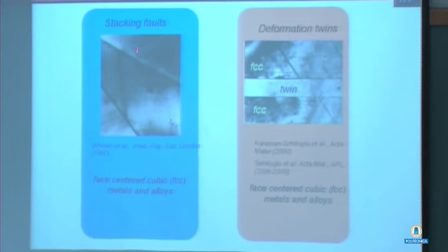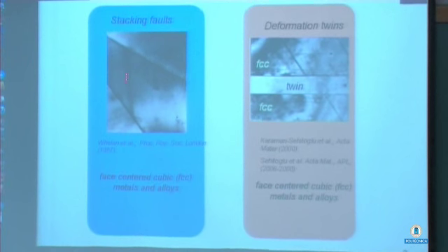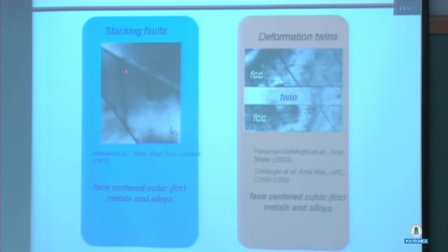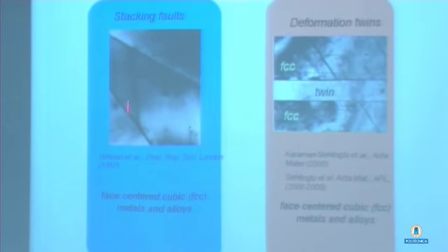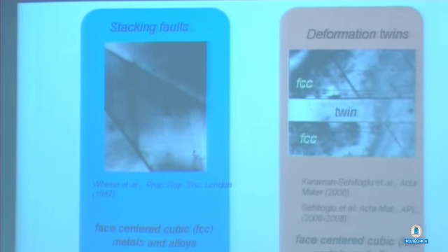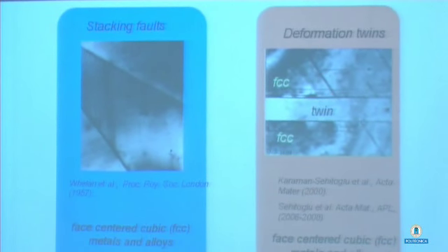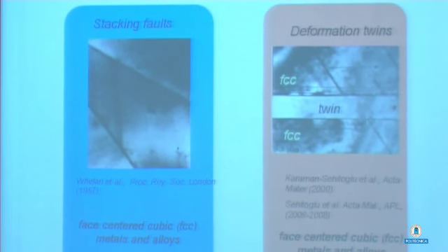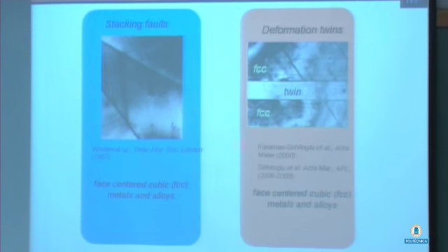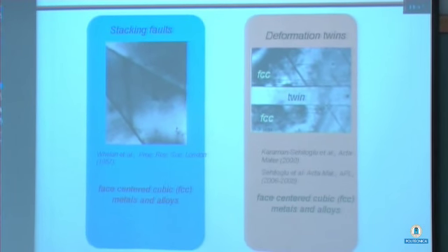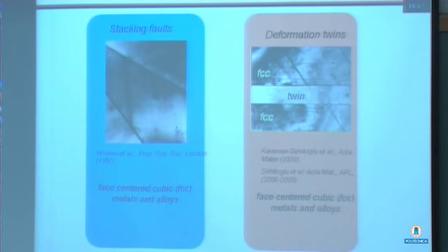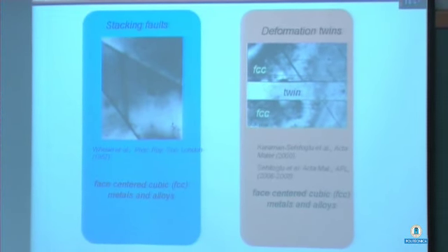In metals, you get stacking faults, and I'll describe what stacking faults look like. In the transmission microscope, they look like these fringe bands or fringe patterns, and they are observed typically in materials with low stacking fault energy, things like stainless steels and some FCC pure metals. And then deformation twins are formed from stacking faults, and deformation twins play an important role in deformation of many materials, in many metallic alloys.